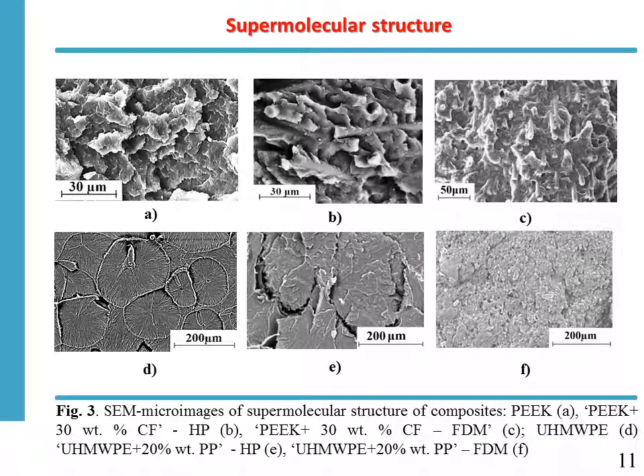So the next slide shows the supermolecular structure of two types of polymers or polymer composites. That is the neat polyether ether ketone. At the center, figure B, it is a composite loaded with 30 wt.% of carbon fibers produced by hot pressing, and on the right you see the composite of the same composition but manufactured by fused deposition modeling. You can see that the structure on the right is dense, and the distribution of the fibers is uniform.